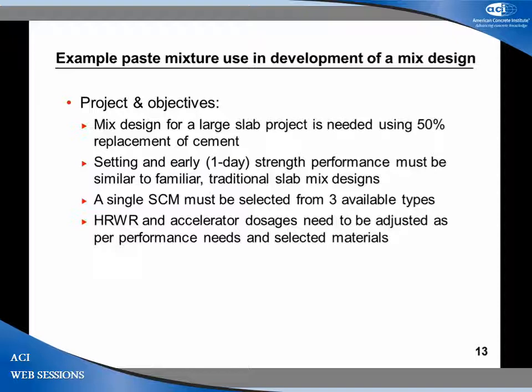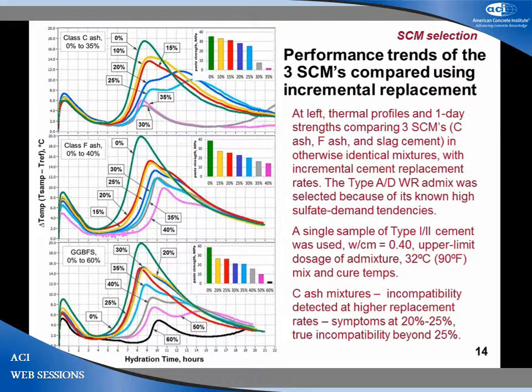Now, one of the things that we do on the front end that may be particularly useful is to evaluate different candidate materials for their potential to misbehave, incompatibility, if you will. And to do this, you don't necessarily have to replicate the concrete mix design that you're interested in, but you might take an aggressive set of proportions that you might have experience with, maybe even experience some issues with in the field, and subject your different SCMs to different replacement rates to see how they compare. And this is just an example of that, thermal profiles and one-day strengths in the bar charts.